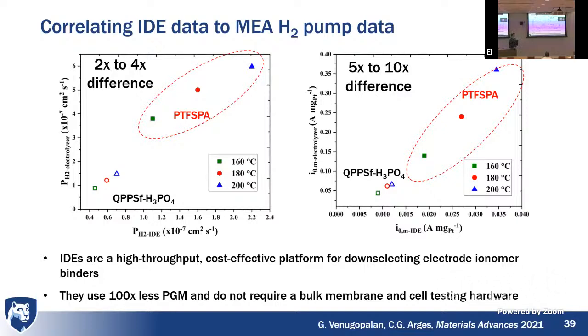If we look at the exchange current density, which is sort of a proxy for the reaction rate coefficient, we're within a factor of 5 to 10. So it's not perfect for this model system, but our argument is that this can be used as a high throughput, cost-effective platform to down select promising new binder materials. We use 100 times less platinum group metal. We don't need a membrane, and we don't need cell testing hardware.